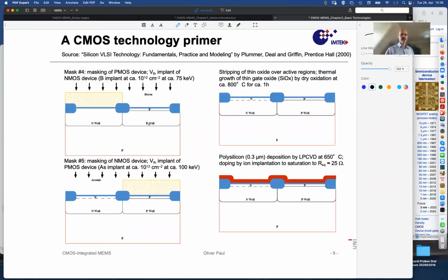So on the left with the P well, we do some additional boron implantation to make it slightly more P doped. Now you see that the number of charges, or the number of boron atoms, is lower, because we will not want them to go very deep. And we are not implanting them at a very high voltage. We want them to remain more close to the surface. And that is happening at these lower energies.